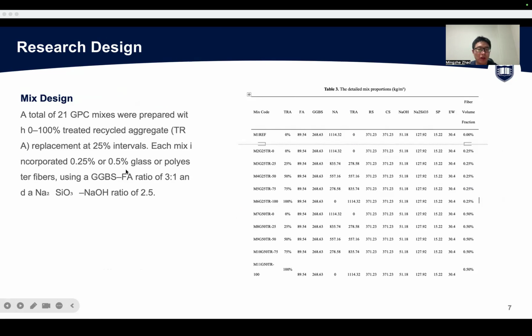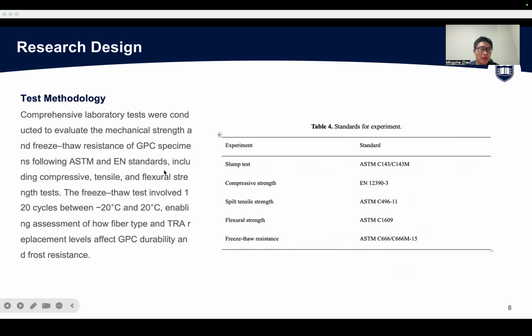And in total 21 GPC mixes were prepared with 0 to 100% treated recycled aggregate replacement at 25% intervals. Each mix incorporated 0.25% or 0.5% glass or polyester fibers. You can see from the table on the right-hand side the detailed mix proportions. And comprehensive laboratory tests were conducted to evaluate the mechanical strength and freeze and thaw resistance.